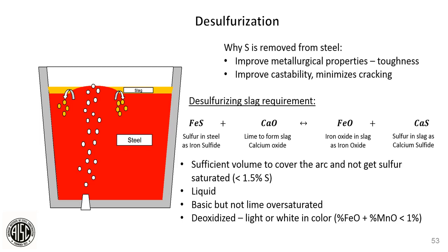So how is desulfurizing done? This is the key component of the ladle furnace, what it's supposed to do. We've got to get the sulfur down so we improve our Charpy V notch results. It improves the castability and minimizes cracking of the semi-finished product. On the left you have a little picture of a ladle, you've got the bubbles running up, you've got the slag layer on the top, and that slag-metal interaction at that interface is crucial, and that's how we get the sulfur out.